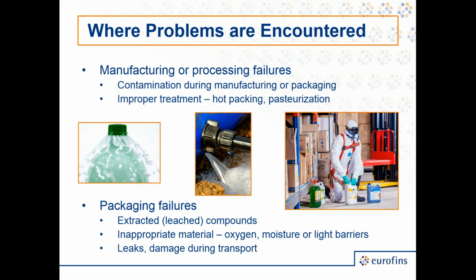The next common failure mechanism is oxygen, moisture, CO2, or light penetrating the packaging, and they cause accelerated failure of the product. So the product tastes good, looks good, it meets all specifications when it goes into the package, but 30 days later, it starts to degrade. And if you have a 6-month or 1-year shelf life, that's going to lead to complaints or potentially recall situations. And then finally, leaks, damage, or exposure to temperature extremes or conditions that were never anticipated when the packaging was specified. And this is becoming more and more of an issue with longer and longer global supply chains.